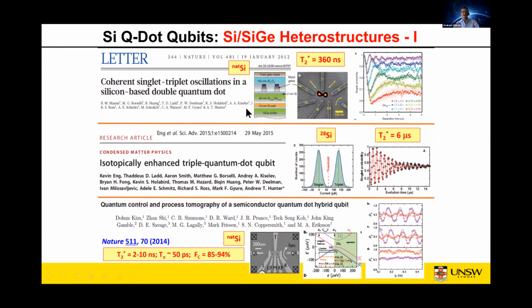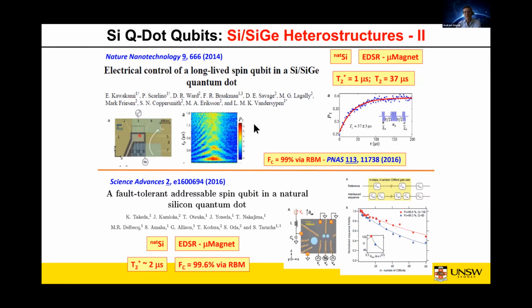And there are a number of demonstrations dating back to 2012, this first paper from HRL Labs in the US, where they, in natural silicon, showed control of, in this case, what's called a singlet triplet qubit. And they then continued 3 years later to show improved control and coherence in isotopically enriched silicon-28. There are a variety of other approaches being explored around the world in silicon germanium. This approach, developed from the University of Wisconsin-Madison, group led by Mark Eriksson, and with theory support from Sue Coppersmith, who recently, a couple of years ago, moved to UNSW in Sydney. This hybrid approach of using a charge spin hybrid qubit has shown a number of great strides over the past 5 to 6 years.